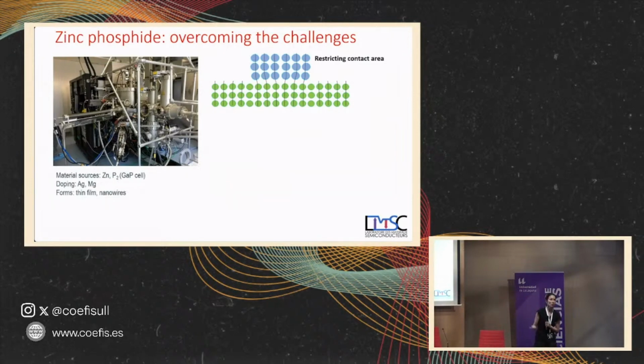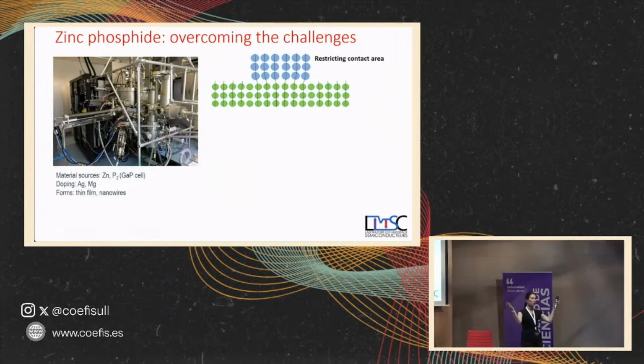In nanotechnology, you start growing in a very small area, and like this, you create tension at the beginning because the structure doesn't match quite, but it's very small, and then the material can expand and become its own. So you start small, and then it becomes bigger.